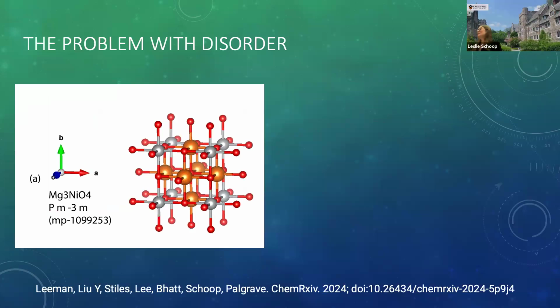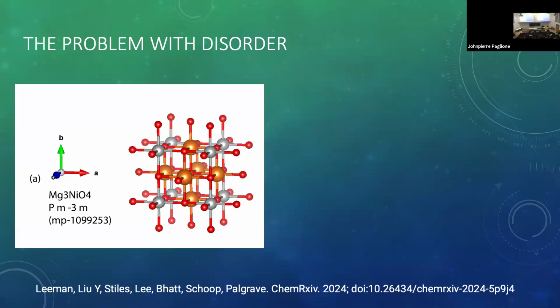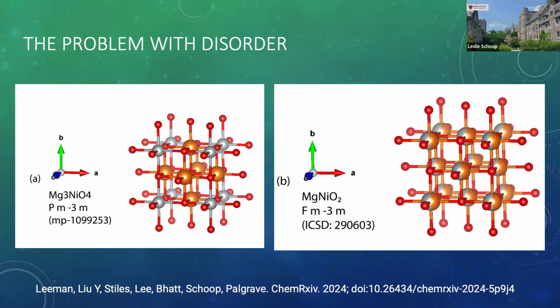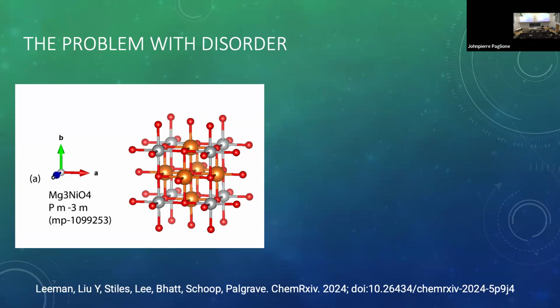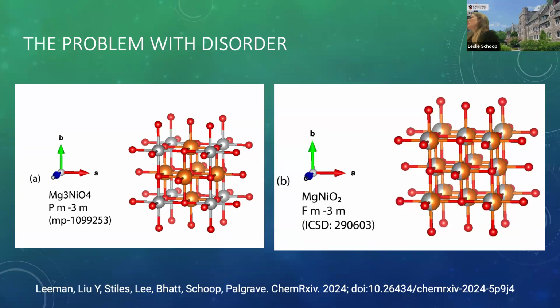Okay, so I want to show you the problem with this border. So here is a material that was predicted in Materials Project, which was one of the targets, magnesium 3 nickel O4, and it has the space group Pm-3m, which is primitive cubic. And you see it's primitive because the magnesium and the nickel here are ordered. They're distinct positions in this crystal structure. So if you go to the ICSD, magnesium nickel O2, or magnesium 2 nickel 2 O4, if you want to put it in the same ratio as there, is reported. And here you have random occupation of magnesium and nickel, 50-50 on each site. And in this case, you get a face-centered crystal structure. It's a rock-salt structure. Okay? So that's a known structure.